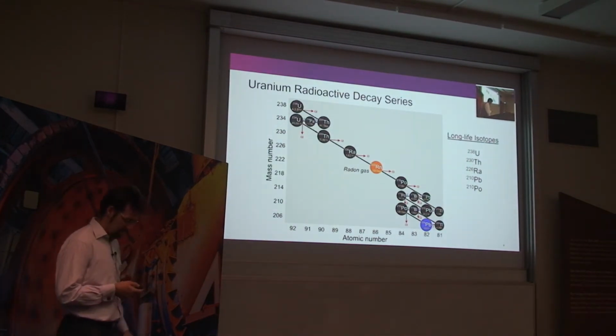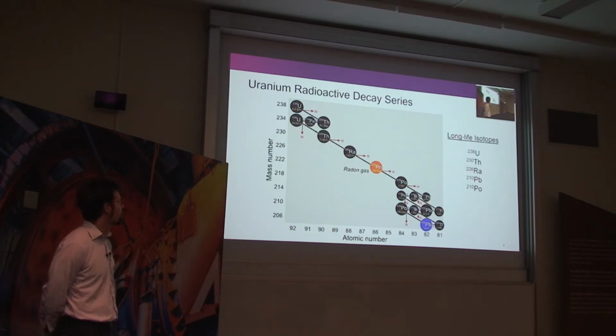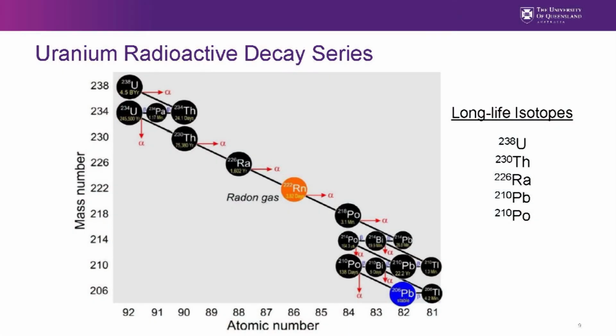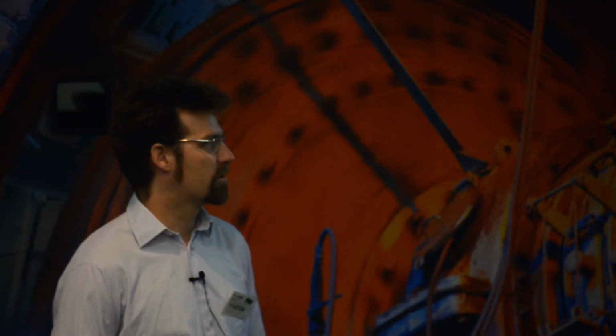This is a slide, just a little bit of background about uranium, and it's just the uranium radioactive decay series. So up here on the top left is uranium 238, and it decays through this series, different elements and isotopes, through thorium, radium, radon gas, polonium, lead 210, polonium 210, and eventually to stable lead 206. So when we look at the radionuclide distribution in the different phases, we tend to focus on uranium 238, thorium 230, radium 226, lead 210, and polonium 210, because they provide the most substantial contribution to the overall radioactivity of the samples.